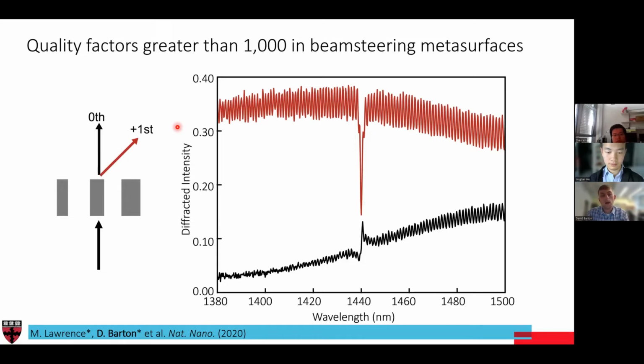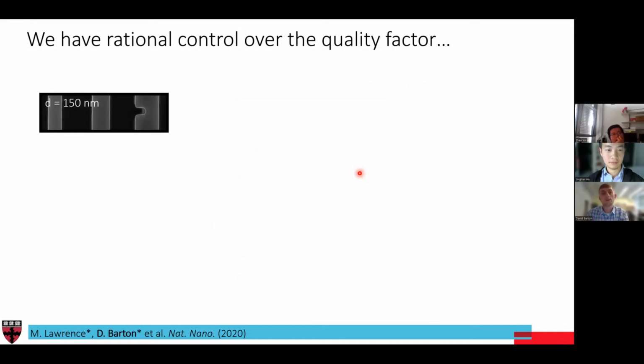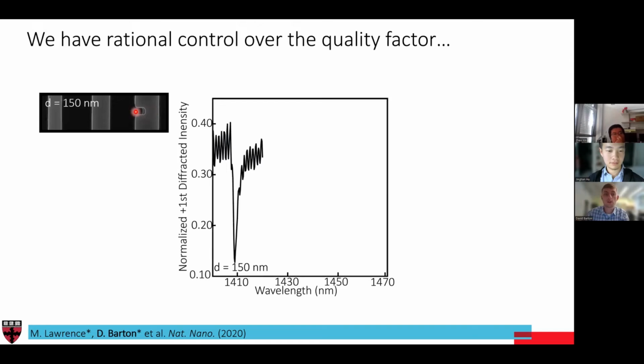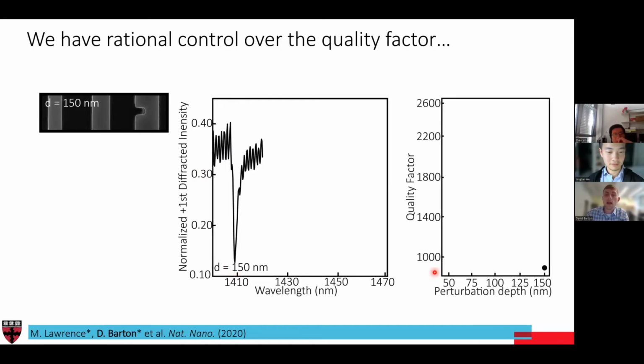And we have this high Q mode that appears in its spectrum. If we extract the quality factor by looking at its line width, we find that we're able to engineer a quality factor in this case of about 1500 in this structure. This is very interesting. It's maybe a two order of magnitude improvement in the quality factor of these sorts of devices. It's also the first time we've been able to demonstrate this in this type of nanophotonic structure. But we can play a lot of games with this. We also made a series of samples where we changed the geometric parameters of this structure. These are all SEM images, and then we have the diffraction into the first order and the extracted quality factor.